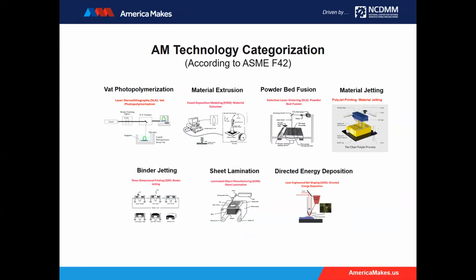In binder jetting, the material to be jetted is not the material of the part, but the binder. So we have powder material in the powder bed, and the binder is jetted to bind the particles in the powder together according to cross-sectional geometry, and then you build the part, and often it's called a green part. You may have to infiltrate with some of the materials to have strength, or sinter the part after it's built.